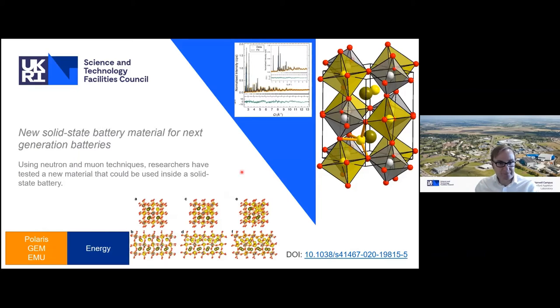In fact, these figures down here, apologies, I made them a little bit too small. If you concentrate on the lithiums, this is how the structure changes as you load it up with lithium. At the highest lithium concentrations, the lithium actually generates LiO4 clusters, which locate on a particular site, the A site, within this double perovskite structure. So neutrons give you an absolute determination of where the atoms are and what the atoms are. You've got a really powerful determination of the structure.